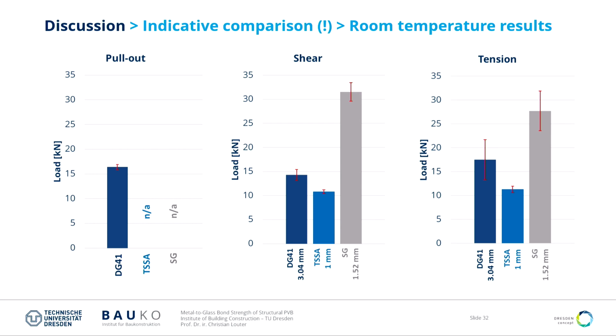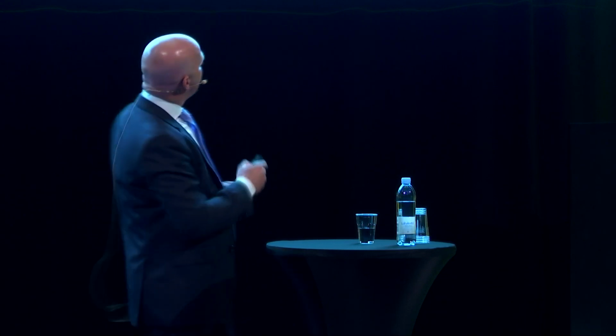And this is then for the tension results. Again, if you compare it to other materials, you can see quite high scatter there, but we think it's due to the inclination, as I said. TSSA has this value, and SentryGlas has this value. You have to be aware, of course, that for SentryGlas, this value will go down quite significantly for higher temperatures because it's a viscoelastic response. For TSSA, these values are quite stable because they are less temperature sensitive. We don't have information yet about the temperature response of the structural PVB, so that's why we should do more testing here. Nevertheless, you can see that the structural PVB has a good performance and can compare to other materials on the market.